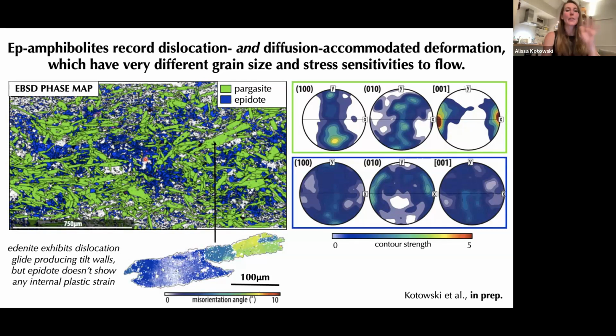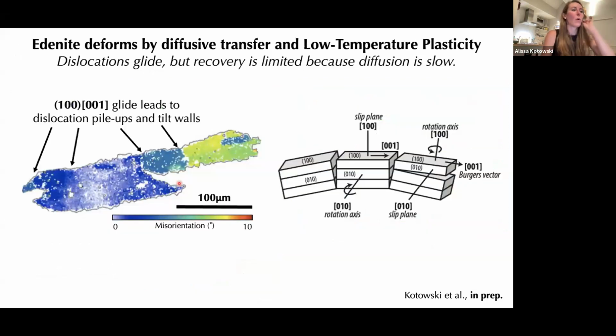What I think this means is that at the scale of this microstructure, we're seeing evidence for coupled dislocation and diffusion accommodated deformation. So this is important because dislocation and diffusion accommodated deformation have very different grain size sensitivities and stress sensitivities to flow. So the fact that we have both of them operating together in concert probably gives us plenty of opportunity to create internal stress heterogeneities and internal stress changes that might eventually lead to something that resembles a slip transient. But let's zoom in even more and think about how this might work at the scale of the amphibole here. So we have actually also two deformation mechanisms operating just in the amphibole, even if we ignore the epidote.